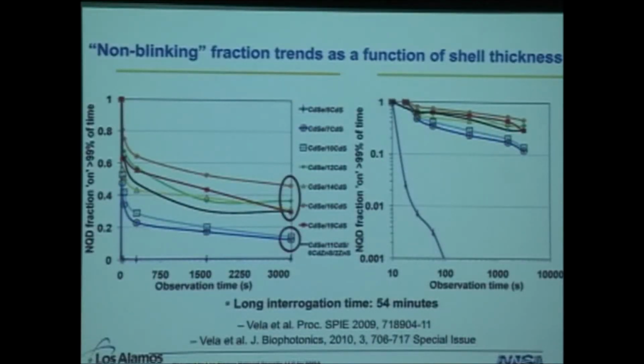Anyway, I mentioned the shelling is significant in terms of the number of shells required to achieve the non-blinking behavior. So again, here we're looking at the fraction of an ensemble of quantum dots that are on for more than 99% of the time, that time being about an hour. And so therefore, this is the non-blinking fraction.